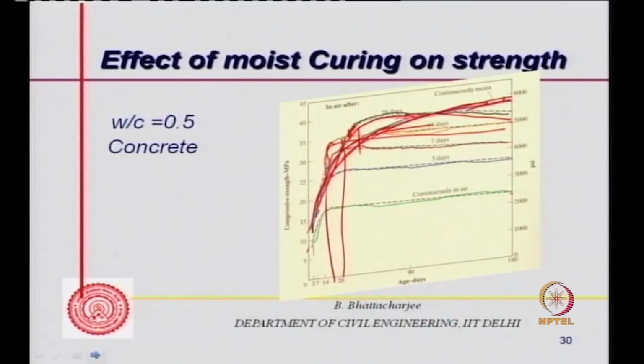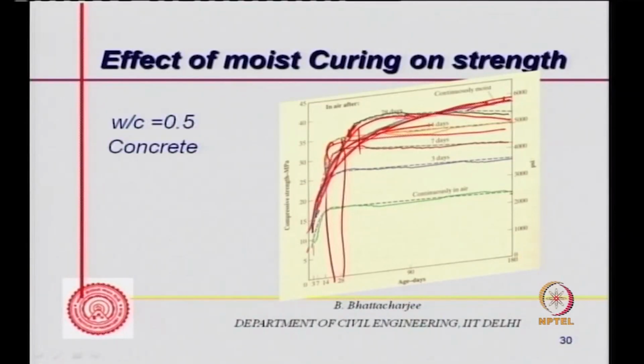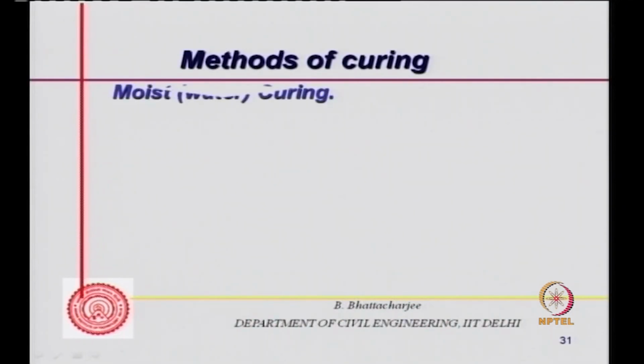Compressive strength is a function of curing age. And if I continuously moist cure it, then this is what I get. It increases significantly, and will go on increasing continuously. For strength gain, I need some amount of minimum curing. The more moist curing I do, the more strength concrete will gain. Methods of curing: obviously water curing is the number one.